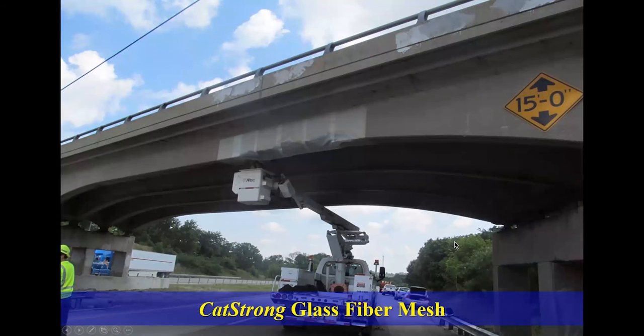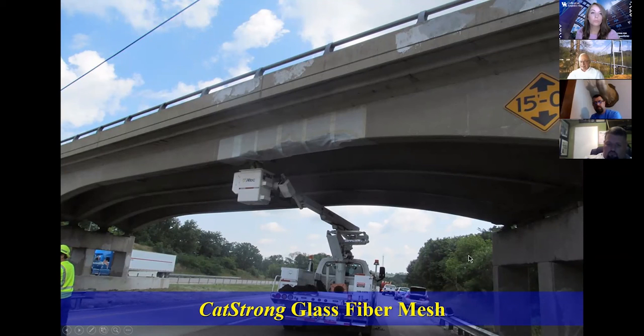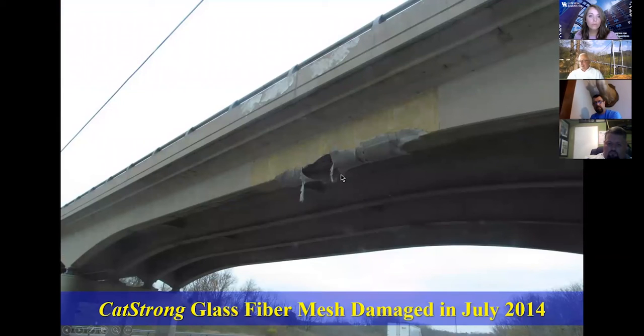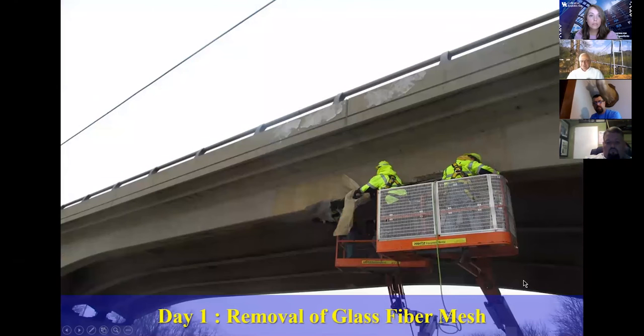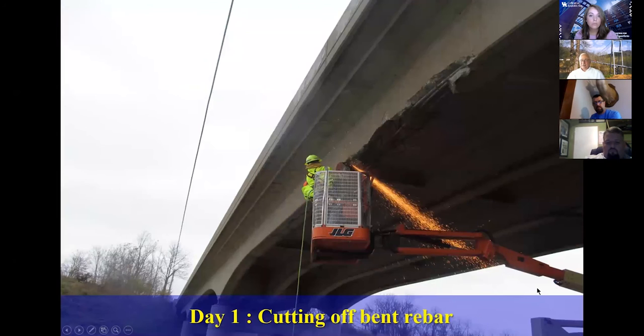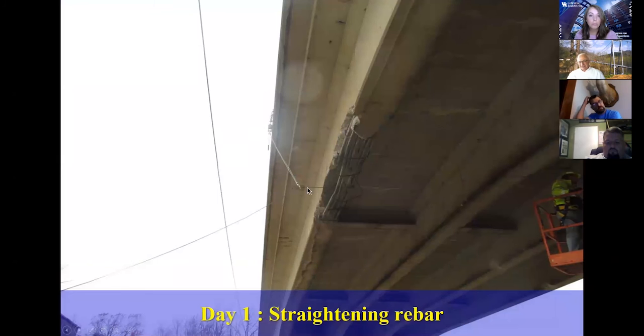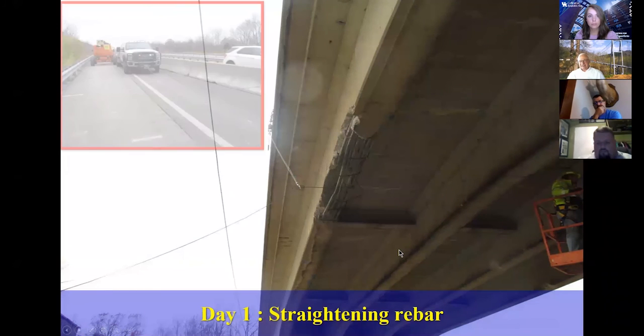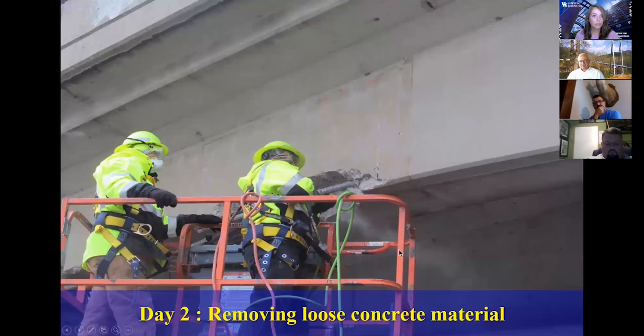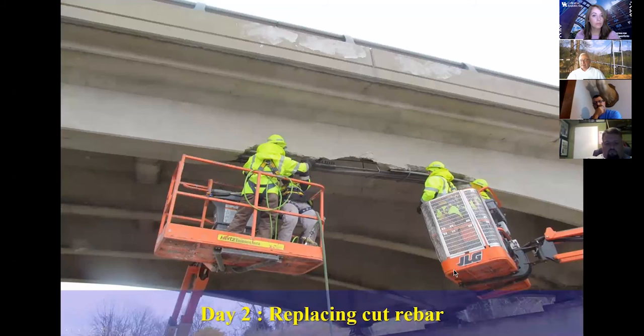Since we could not do the repair right away, we usually put glass fiber mesh to make sure that no debris falls on the public until we get to the repair. As it happened, another overhigh truck came and hit that mesh. So during the repair process, we removed the mesh, we cut the bar, we straightened it. We used this steel cable that goes to a truck on the bridge to straighten some of these rebars. And of course, we sandblast the rebars. Here we are putting the connector for the splice to splice the rebar.